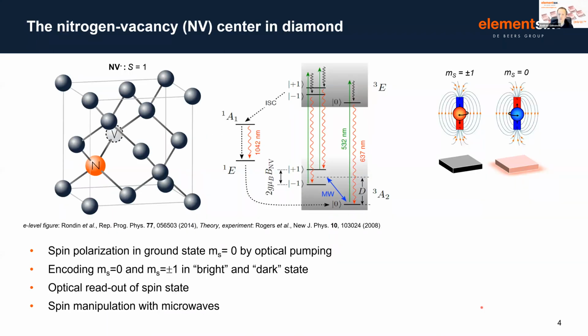So one of the reasons why diamond has become such a big part of emerging quantum sensing technologies is because of a particular defect or color center that we can find within special diamonds. And this is the nitrogen-vacancy center, or for short, NV center. Now, throughout the last few decades, there's been an awful lot of really beautiful experimental and theoretical work to really understand, to begin with, this defect, and then more and more in increasing years actually utilizing the properties of this defect. Now, I don't need to go into too much depth on the beautiful spin physics of this defect, but there are a few key points that I want to emphasize.